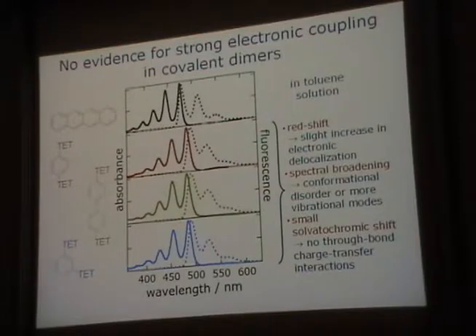So we're really dealing with monomeric tetracene here. We don't see any solvatochromic shift. In other words, there's no charge transfer states nearby to affect this because when we put it in different polarity solvents, we don't see anything change. Right? So there's not any involvement of charge transfer states. They're probably way too high in this molecule to have any effect.